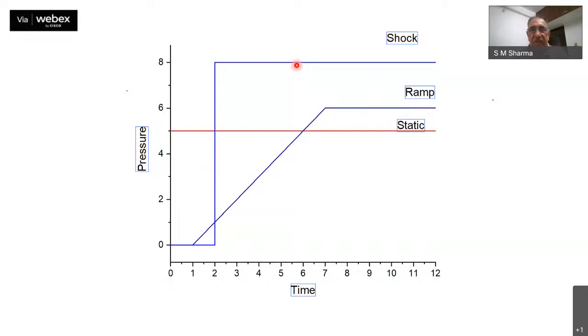We will see how one describes those states, but that comes as a deal. You can't separate these two thermodynamic variables. Ramp compression is in between. You can tweak this rise time in a systematic manner so that the temperature increase could be kept very small. So depending on the rise time, one can get the states at one limit being almost close to static and the other almost going to the shock compressed state.